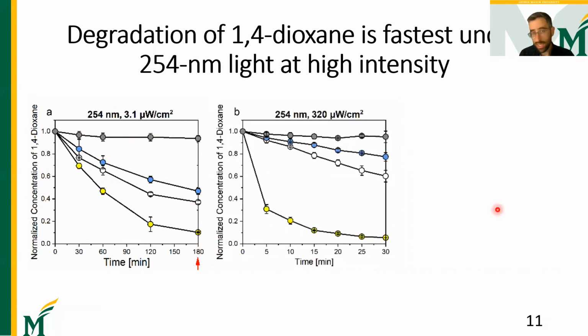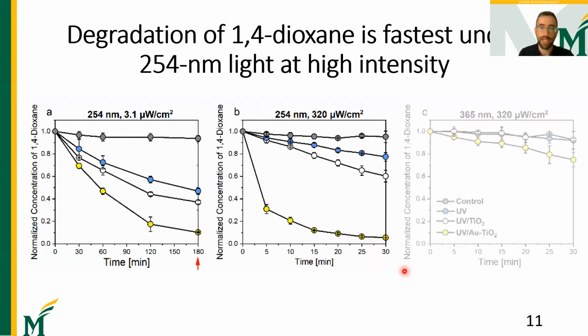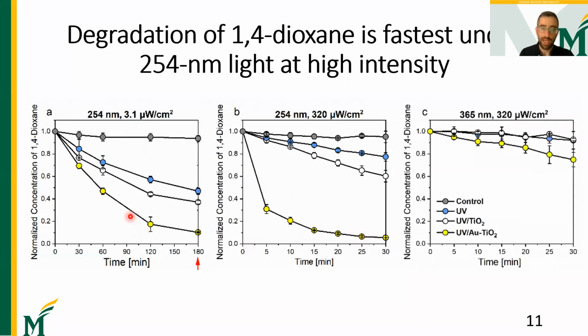Next, by boosting the UV light intensity by 2 orders of magnitude, we see a dramatic improvement in the performance, especially with the gold TiO2. And note also that this is only over 30 minutes. Finally, by increasing the wavelength to 365 nanometers, keeping the intensity the same, we notice that there is a significantly slower degradation. Okay, so 2 main takeaways here.